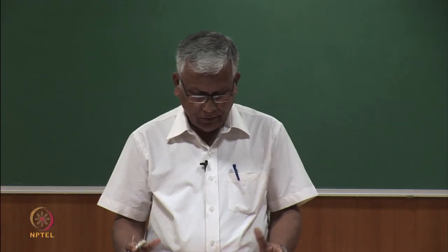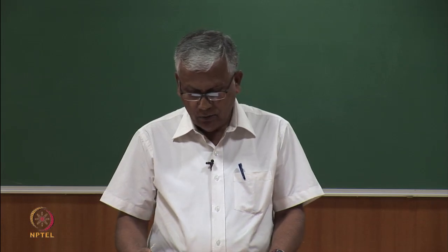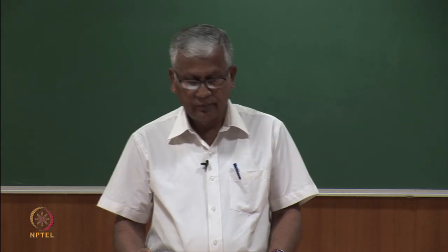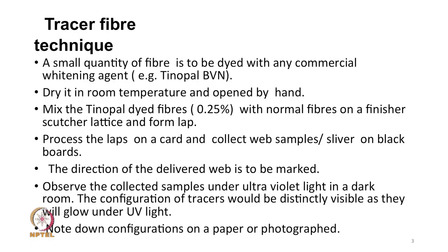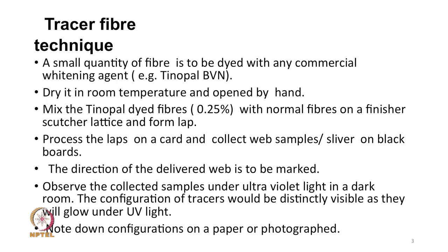In this technique, first of all, a small quantity of fiber is dyed with any commercial whitening agent like Tinopal BVN. After dyeing this, we dry the fibers at room temperature, and once it is completely dried, we have to open it by hand using our fingers. Once the fibers are separated from each other, now these tracer fibers are mixed with normal fibers.